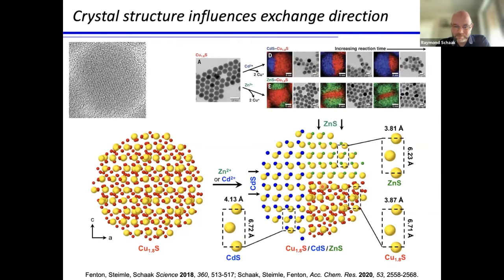So for example, if you do a partial cation exchange with cadmium sulfide, cadmium sulfide and copper sulfide are not inherently miscible. So their preference is to remain segregated. Ditto with zinc sulfide and copper sulfide. If they remain segregated, they need an interface. Interfaces are inherently higher energy. So to minimize the interfacial energy, you want the smallest number of interfaces, and you want the interfaces to form that are the best lattice match, the most epitaxial with one another.